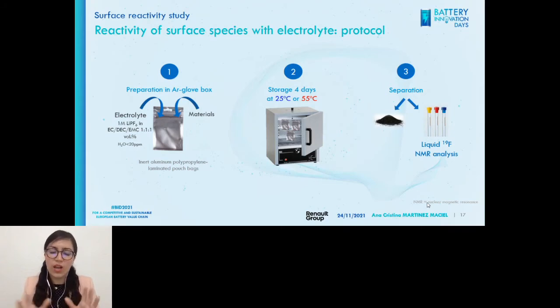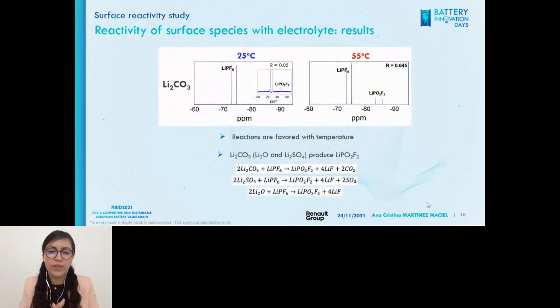I will just show you one result because of time, but this is what I think summarizes it best, because carbonates are always at the surface of NMCs. This is a result of storing lithium carbonate with electrolyte and storing at 25 or 55 degrees. We see that there is a doublet peak of LiPF6 - this is normal, it's contained in the electrolytes of commercial batteries. And then we also see a doublet that corresponds to lithium difluorophosphate, LiPO2F2.